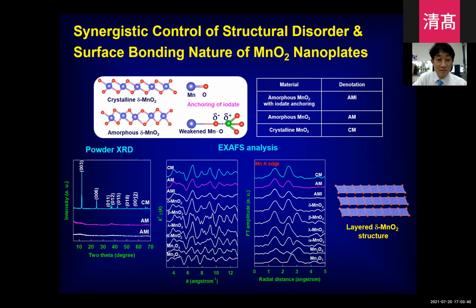We stabilized highly oxidized iodate nanocluster on the surface of the manganese oxide nanosheet. By using the XAS analysis, we confirmed the formation of the layered structures, even though some of the material shows X-ray amorphous.